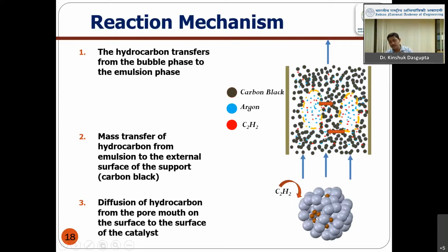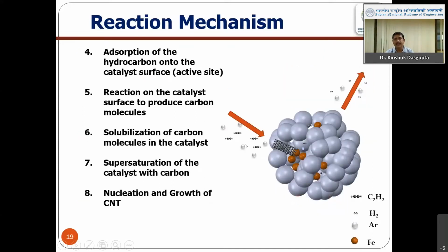Once they reach there, they get adsorbed on the catalyst surface. These are the iron nanoparticles, and the hydrocarbon first gets adsorbed onto them, and after adsorption there is a catalytic reaction, called pyrolysis. The hydrocarbon cracks into carbon molecules and hydrogen comes out. So there is a reaction on the catalyst surface to produce carbon molecules, and these carbon molecules have limited solubility in the iron catalyst.